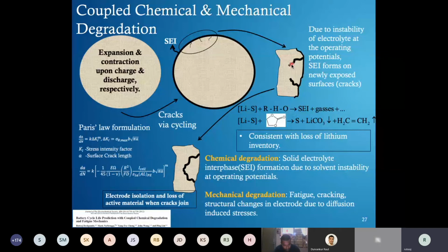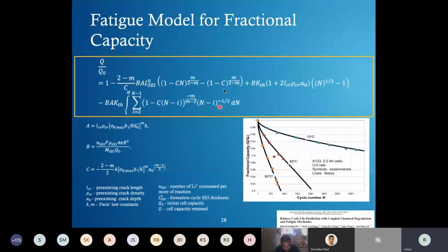This kind of degradation is called coupled chemical-mechanical degradation. Remember, if there was only mechanical degradation, it may not be as bad. But since we have these chemical reactions which are eating away lithium from the system, it becomes more harmful. So you can use, say, the classical Paris's law to understand what the crack growth in the electrode particles would be. Based on that, you can come up with an equation which will tell you how much the capacity loss would be if you are charging and discharging the cell at a particular rate of operation. We could use this equation on A123 data, and we could basically fit the data very well based on the physics again. So this is the third type of degradation mechanism basically happening within the electrode particles.